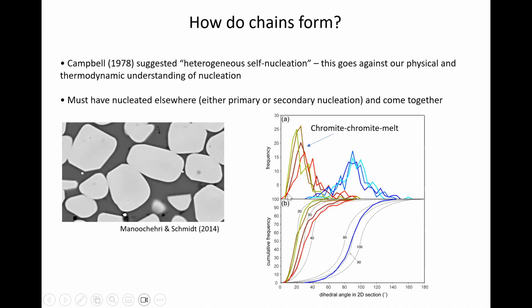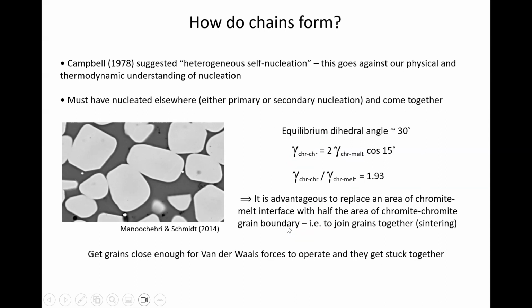And this is my work here. So the chromite melt dihedral angles, this is 3 or 4 different experiments. The median value is about 30 degrees. So it's a nice low dihedral angle. This is just the force balance between the chromite grain boundary energy and the chromite melt interfacial energy. And what it tells us is that the chromite grain boundary energy is less than twice that of the chromite melt interface.